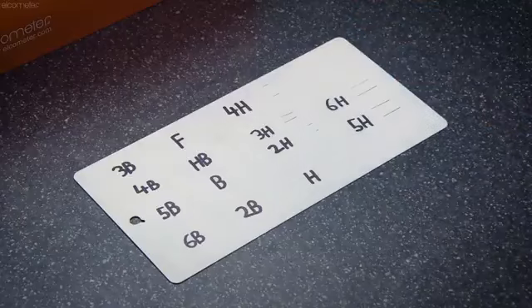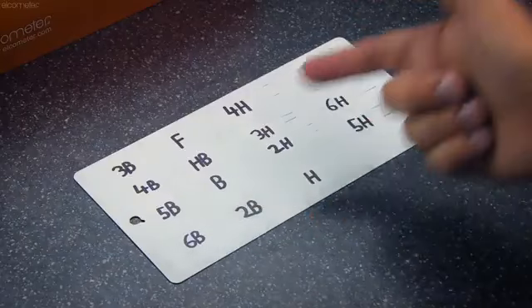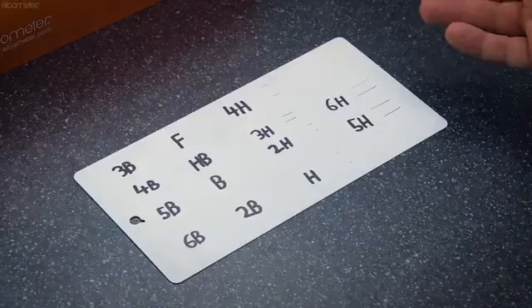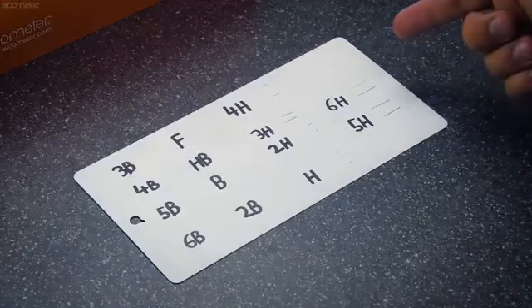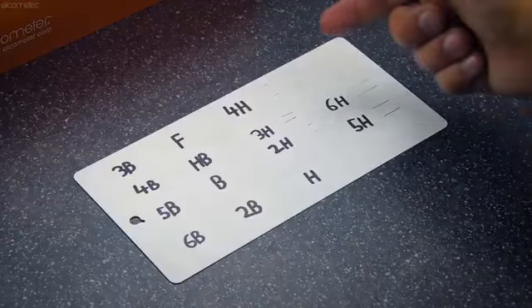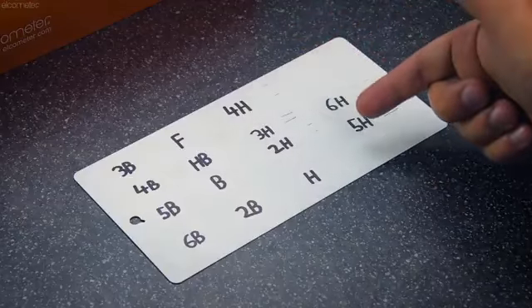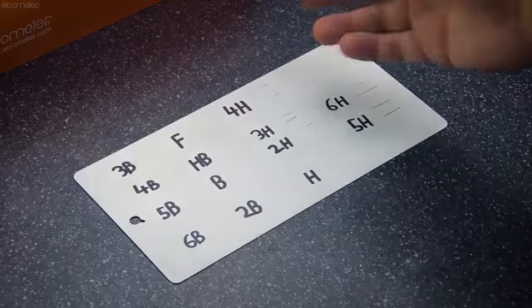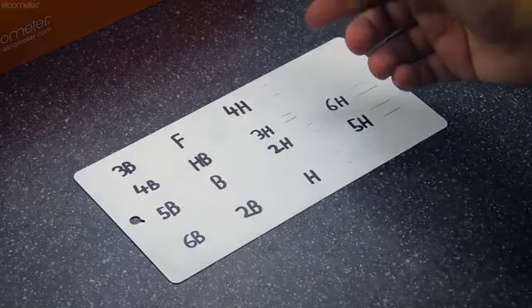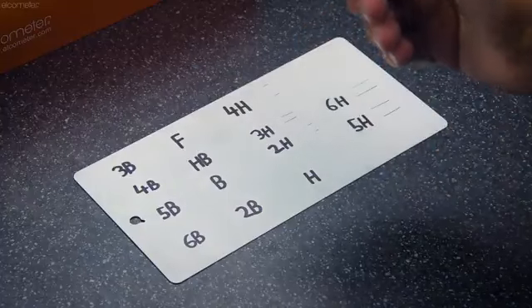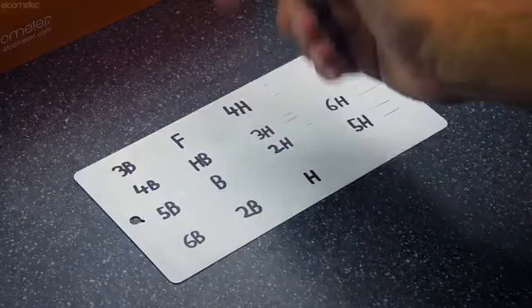So, if we take a look at this test panel, which has results from 6B, soft, all the way through to 6H, hard, and we work down from the hardest pencil, what we can see is that the hardest pencil to make a scratch in the film that's less than 3mm long is H. So, this is the gouge hardness, as all the scratches made by harder pencils are over 3mm in length. As for the scratch hardness, we carry on going from hardest to softest to find the hardest pencil test result that leaves no marking at all, and as you can see here, the result is F.